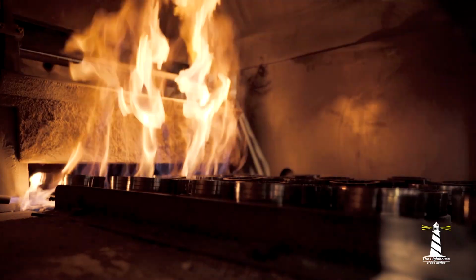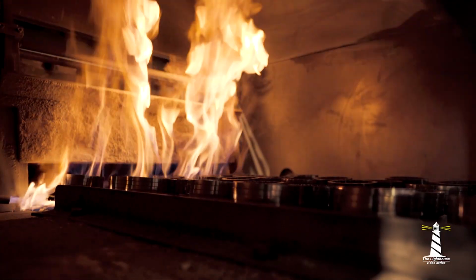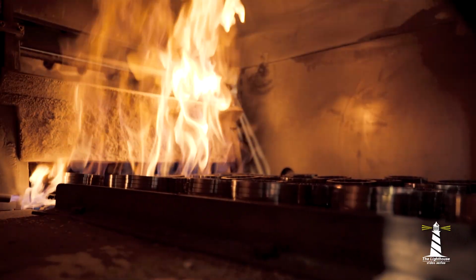We then put the mechanical properties into that material through the sintering process. So the part is conveyed from the press into the furnace. The first step of the furnace is to burn out any of the lubricants from the compaction process. And then it enters into a high heat zone, which, for the average steel alloy is around 2100 degrees Fahrenheit or 1120 degrees Celsius.